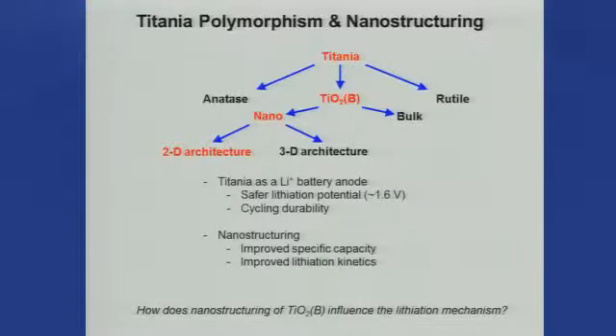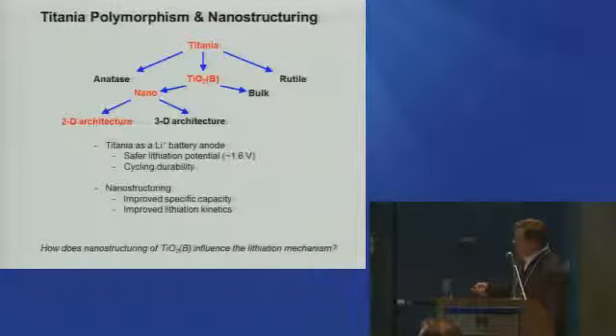But in the new synthesis techniques, people have discovered this intermediate kinetically metastable phase that's known as TiO2b, or bronze for short. It's got a different crystal structure, but this is primarily done by low temperature synthesis. It's ion exchange, typically from sodium and potassium titanate structures that dehydrate to form crystalline TiO2b, and this can be tuned in terms of its size and the architecture. You can make nanowires, nanorods, nanoparticles, mesoporous networks, and so forth.